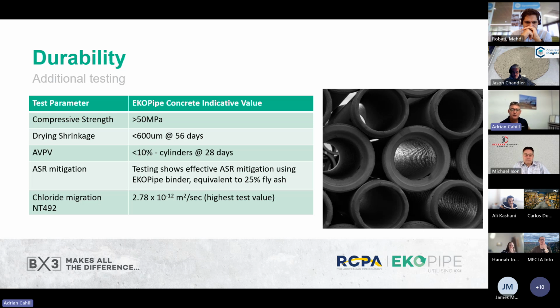There we go. We've done a range of additional testing to largely satisfy asset owners that there's nothing weird going on or fundamentally unusual about the EKOPipe concrete. So these are just some of the parameters, and these are listed in a technical manual that's on our website. But all of these values, depending upon the location, obviously drying shrinkage is pretty universal. AVPV testing is more relevant for those in Victoria. ASR mitigation is quite important. Now, we've done assessments with mortar testing that shows that the EKOPipe binder mitigates actually better than a 25% ash blend, which is what's traditionally used.